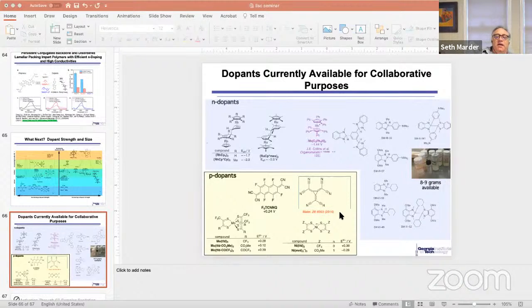And so I talked to you about a case where our dopant was too fast, okay? And it led to formation of charged species in solution, which aggregated, and we didn't get an ideal morphology to get the highest conductivity. Okay, so you could begin to think about using your solvent one way or the other to accelerate the doping process in solution if you want to, before you form the film, if your dopant is maybe too slow, or you could try to back off on the solvent polarity, assuming you could keep things in solution, such that until you get the thing into a film and the concentration goes really high, you don't get doping.